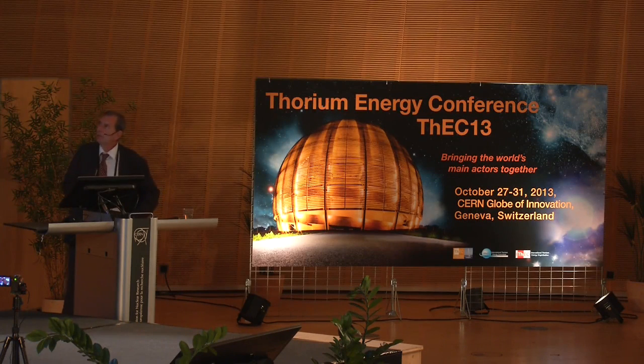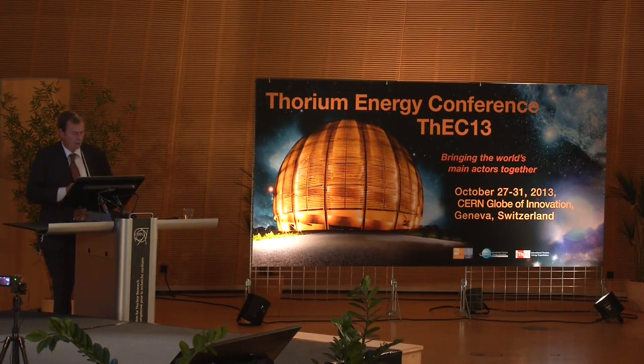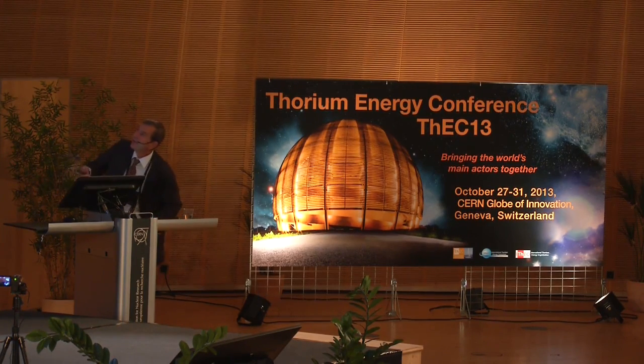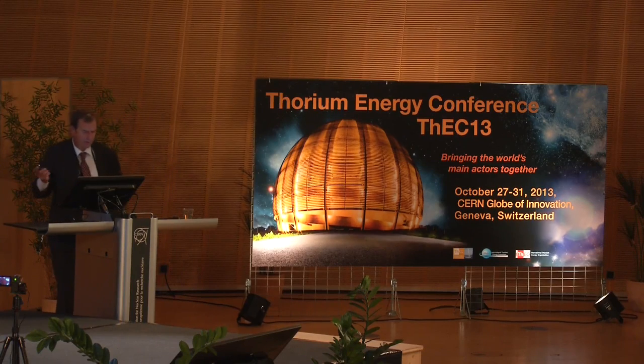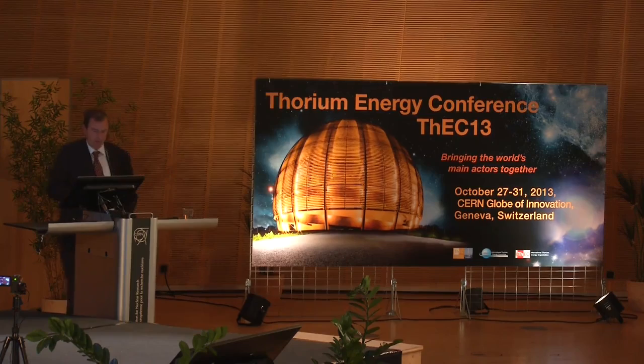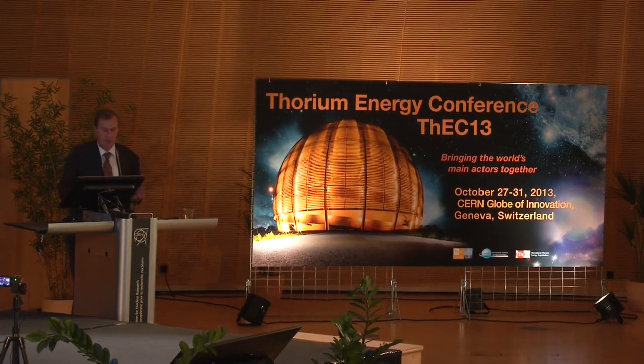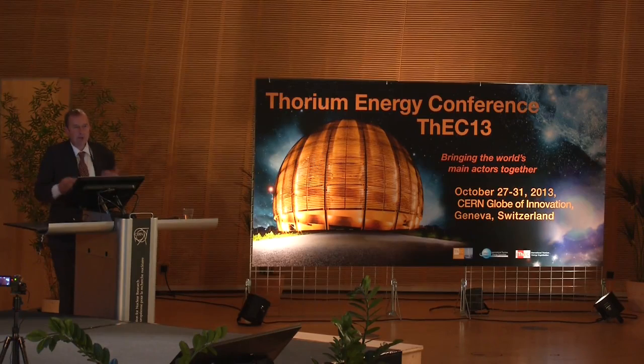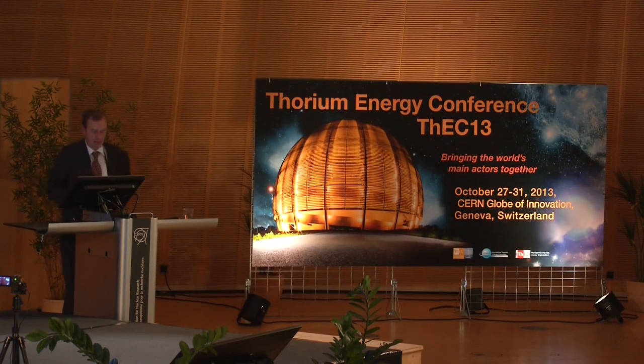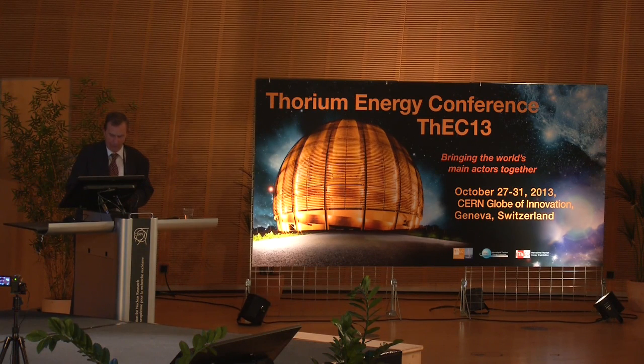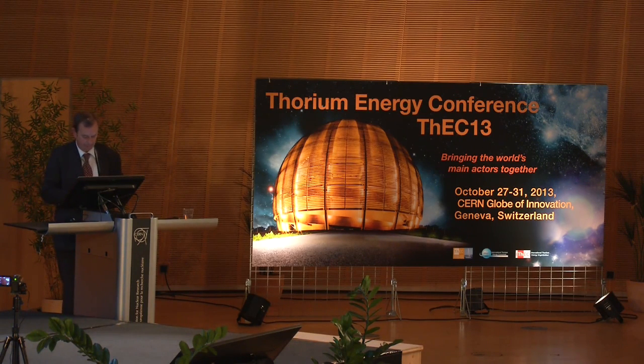Here it's a figure coming from the SCK CEN in the LWR Deputy experiment, where the thorium pins were instrumented, so the measurement of the central temperature was possible. In the light gray, you see the measurement values and the different codes for comparison. And it shows only that nothing is perfect, and the codes, if they are applied before you know the results, don't show very good results, but that's quite normal. You have to have more data and adapt your code in order to get the right results. So the work is certainly not finished before it's possible to license the fuel.